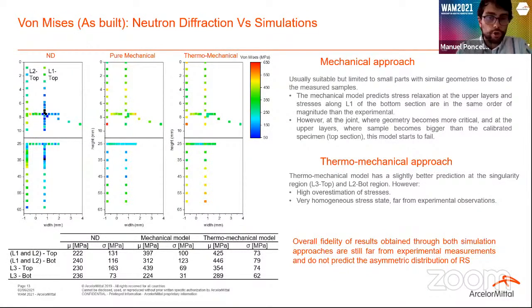So here I compare the stresses predicted by both models with the von Mises stresses measured by neutron diffraction. It's easy to see that there is a big discrepancy between the prediction of both models and the real stress measured experimentally at SALSA. And this is mainly because of the degree of simplification, and they do macro layer activations. So it's very difficult for the model to really predict a stress gradient inside the same printing layer. So in the same XY plane, those models usually give us very homogeneous stresses, while that's not the case.